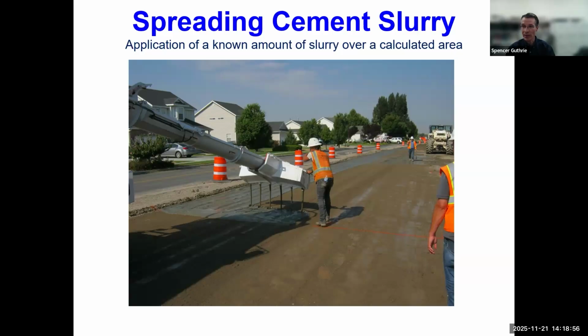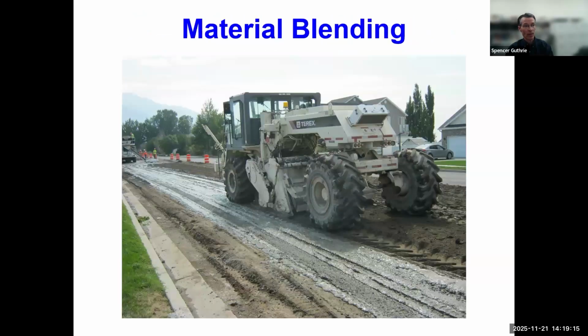And if for some reason they put down a little too much, then we have a grader operator who can just come on over and blade some of that extra slurry off of the high spot onto the spot where it belongs. So we have an orange line. Do you see that across the grade? Just marking the perimeter. We're going to unload this truck onto the grade. And as soon as we start unloading, you see the operation continuing in the far left, then the reclaimer can come on and begin mixing.